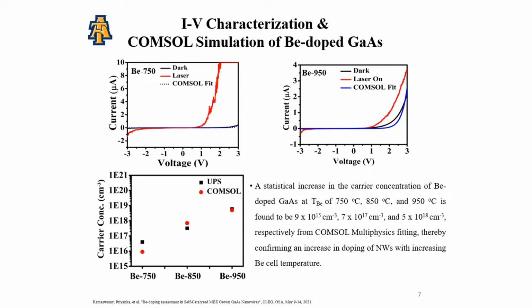From COMSOL Multiphysics fitting, a statistical increase in the carrier concentration of beryllium-doped gallium arsenide at beryllium cell temperatures of 750 degrees Celsius, 850 degrees Celsius, and 950 degrees Celsius is observed and found to be 9 × 10^15 per cm³, 7 × 10^17 per cm³, and 5 × 10^18 per cm³. This confirms an increase in doping of nanowires with increasing beryllium cell temperature.